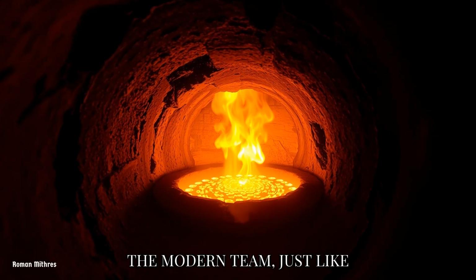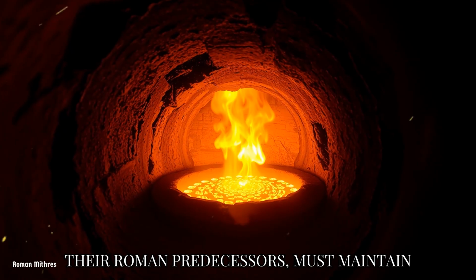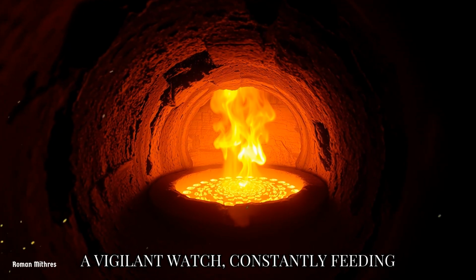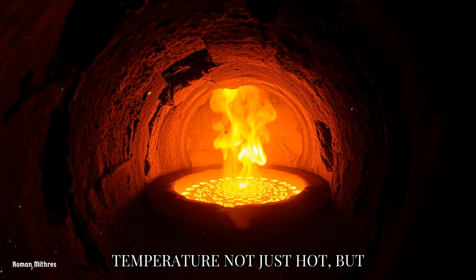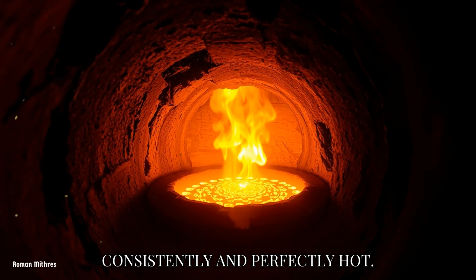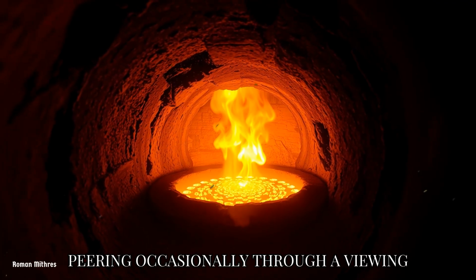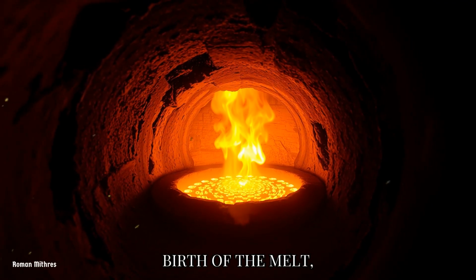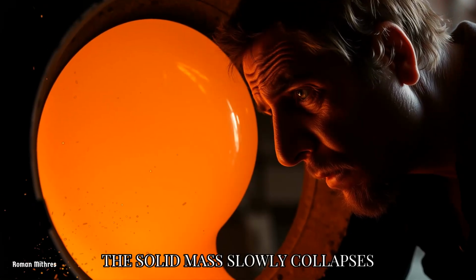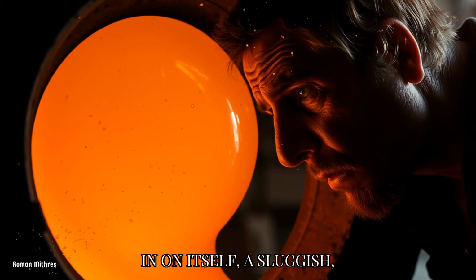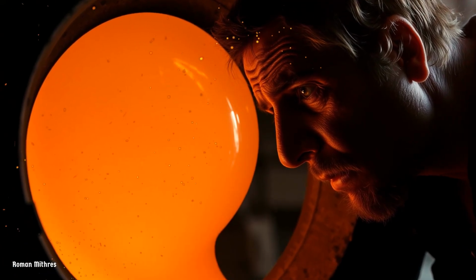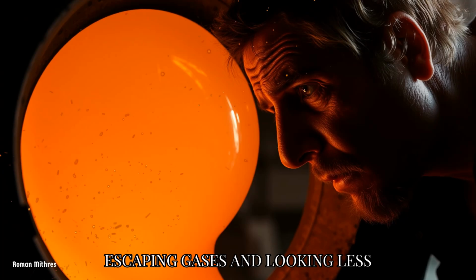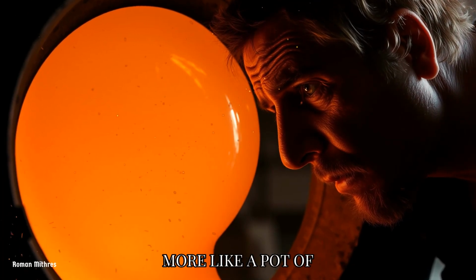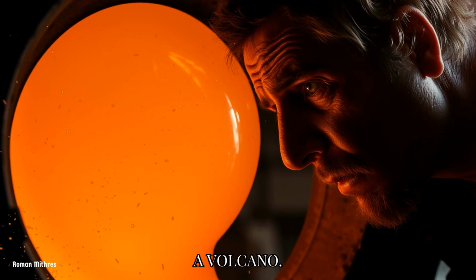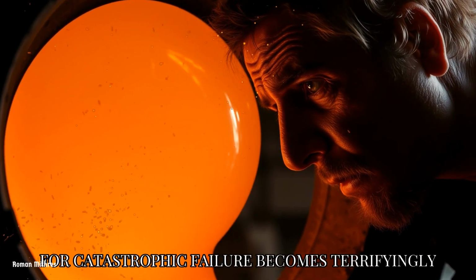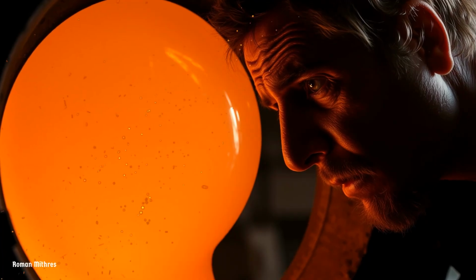The modern team, just like their Roman predecessors, must maintain a vigilant watch, constantly feeding the fire to keep the temperature not just hot, but consistently and perfectly hot. Peering occasionally through a viewing port, they witness the gradual birth of the melt. The solid mass slowly collapses in on itself, a sluggish, bubbling pool beginning to form, thick with a foam of escaping gases, and looking less like a magical substance, and more like a pot of boiling, viscous honey straight from a volcano. This is where the potential for catastrophic failure becomes terrifyingly real.